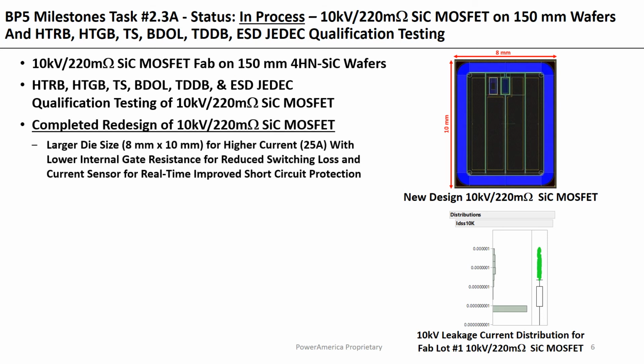We have completed the redesign of the 10 kilovolt, 220 milliohm silicon carbide MOSFET, which is shown here on the right. It's an 8 by 10 millimeter device with a lower on resistance than our previous 10 kilovolt silicon carbide MOSFET and a higher current. It also has lower internal gate resistance for reduced switching losses and a current sensor for real-time improved short circuit protection.